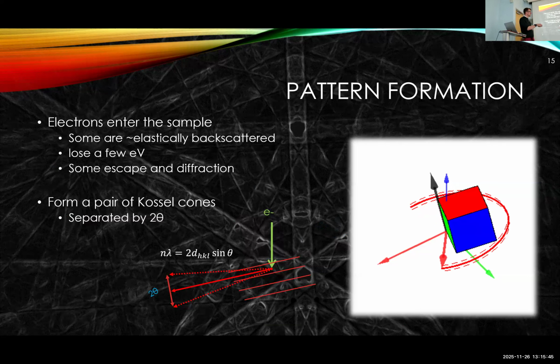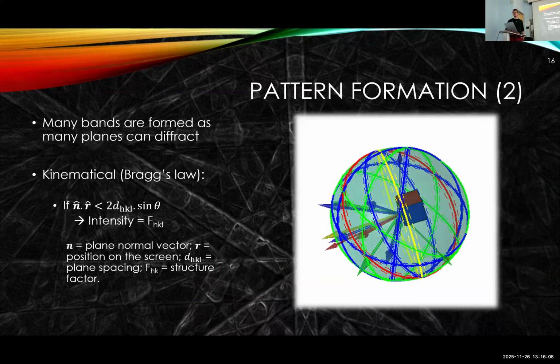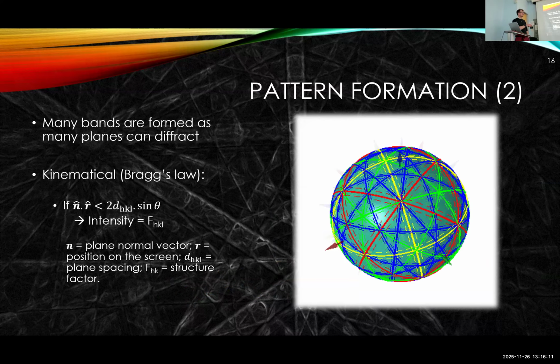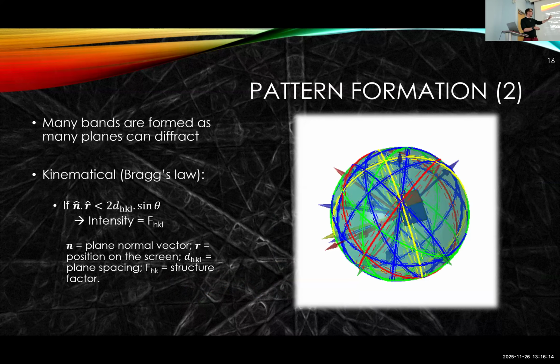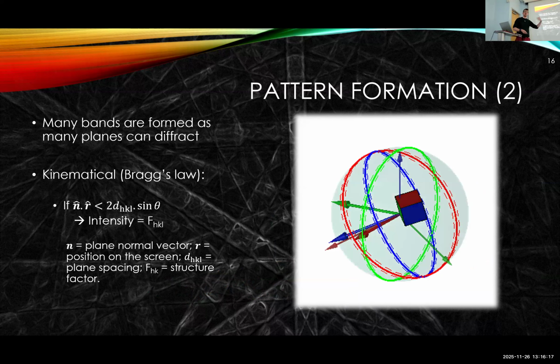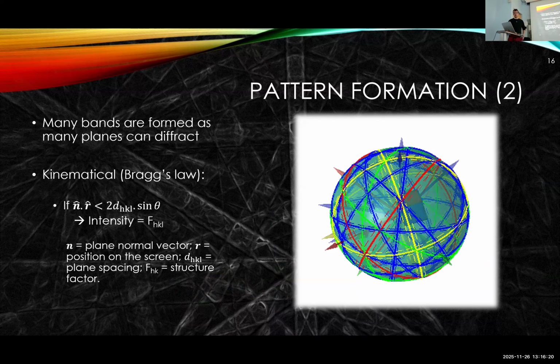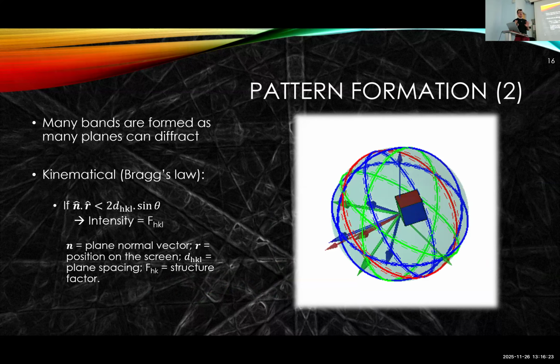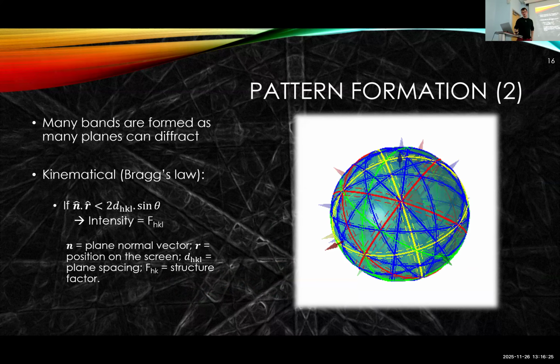In 3 dimensions, of course, this extends as we expand this into a circular band on our sphere. And we see the separation of the band edges, 2 theta, and anything within those dashed lines are our bands of raised intensity to a first order approximation. And this is showing it for a particular 100 type direction in my cube. If I then expand this across multiple crystal planes, we can build up our crystal Kikuchi sphere. And this is a simple kinematic case with all the bands indexed. And of course, we can do more fancy maths to give us the cool sphere I showed you earlier if we require. I can discuss the fancy maths, but it's unimportant for today's discussion per se.